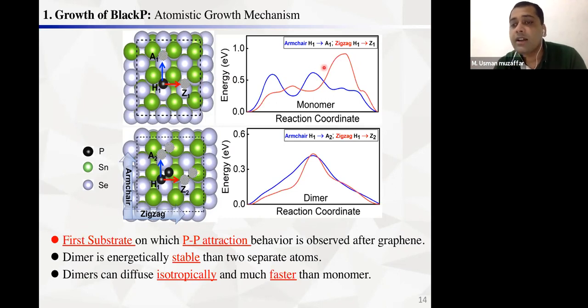So there is also anisotropic behavior, because this is a high diffusion barrier and this one requires a low diffusion barrier. So anisotropy is there. More interestingly, when we put two phosphorus atoms, we find that they prefer to form a dimer instead of staying apart. They prefer the dimer, and they have a higher binding energy than that of two single, separate atoms.